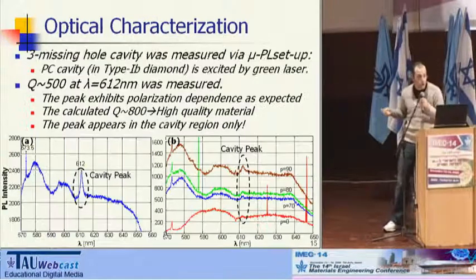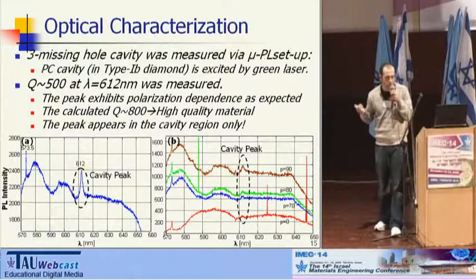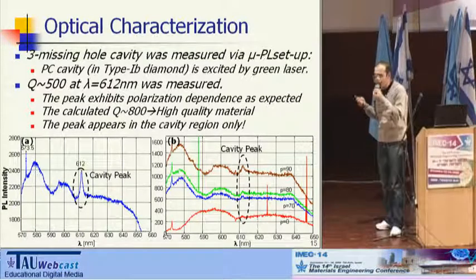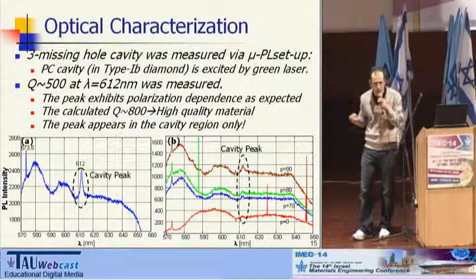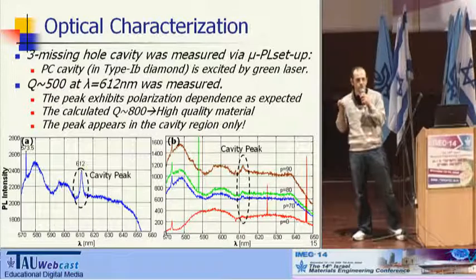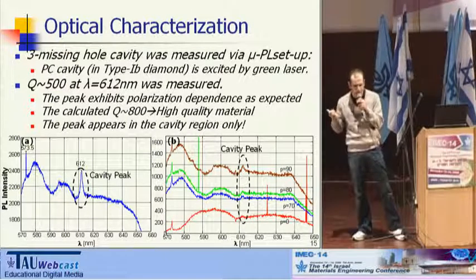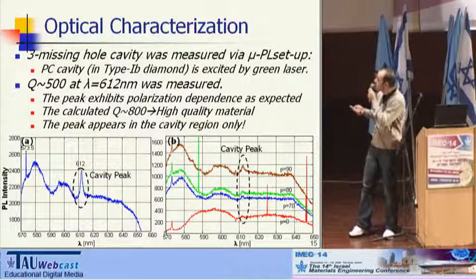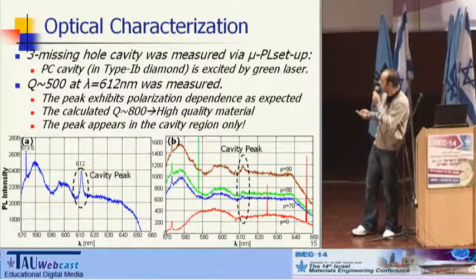Now, to the optical characterization. We have excited our cavity that I have shown you a few slides ago with a green light and measured the photoluminescence in the red light. The photoluminescence shows this magnificent peak at 612 nanometer.